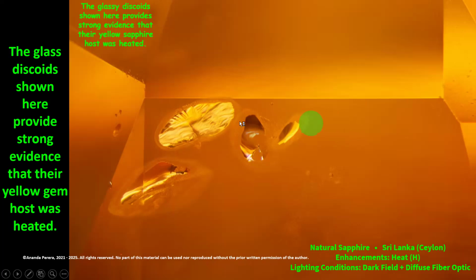Another evidence. These are the glassy discoids. Watch this and remember. A glassy discoid shown here provides strong evidence that this yellow gem host was heated. It is a Sri Lanka natural sapphire, heated yellow sapphire. So heated is mentioned here with the letter H. Lighting conditions: dark field plus diffuse fiber optic. Two conditions together, then we can see these are called glassy discoids. Remember what the glassy discoids are? Very important.